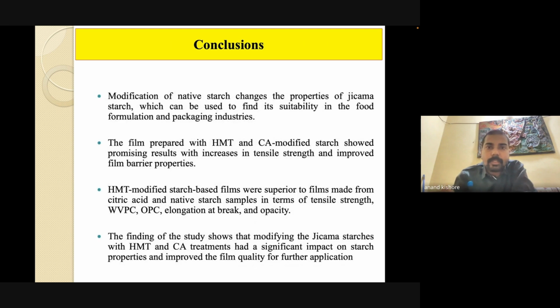So the conclusion from my research project is that modification of native starch changes the properties of jicama starch, which can be used to find its suitability in food formulation as well as the packaging industry. The film prepared with HMT and CA modified starch showed promising results, with increased tensile strength and improved film barrier properties. HMT modified starch-based film is superior compared with the citric acid in terms of tensile strength, water vapor permeability coefficient, oxygen permeability coefficient, elongation at break, as well as the opacity. So the findings of the study show that modifying the jicama starch with HMT and CA treatments had a significant impact on starch properties and improved the film quality for further applications.